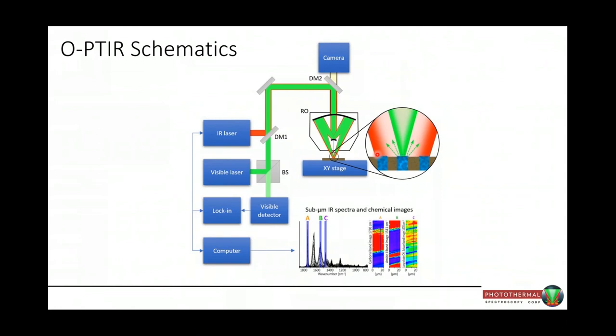If the sample absorbs the IR light, it photothermally expands, and the refractive index changes and the sample actually expands, and they modulate the reflected green light. So the green light coming in is not modulated, the IR laser light is modulated, and the reflected green light is only modulated when you're in a region where the IR absorbing species is. You then send that laser back to a visible detector, and you tune to the modulation frequency of the pulsed IR laser. From that, as you sweep the laser wave number, you can get the spectrum, or you can sit at a particular wave number and get an image.